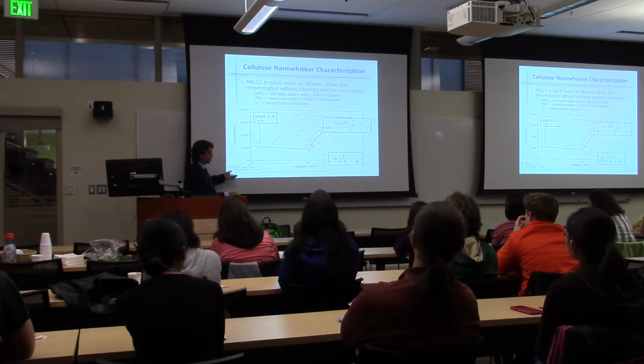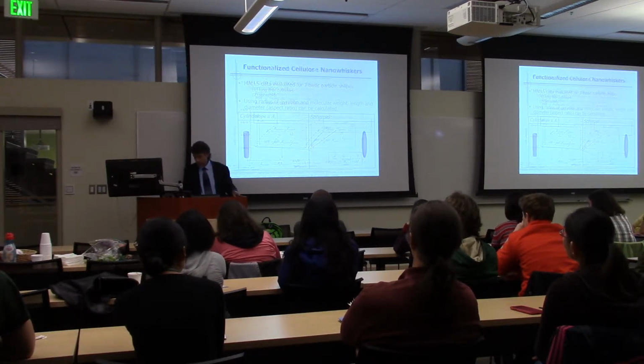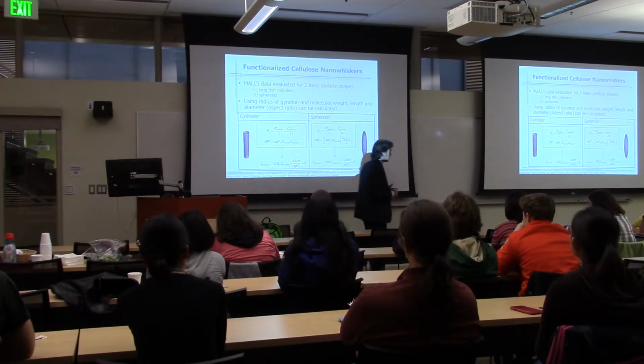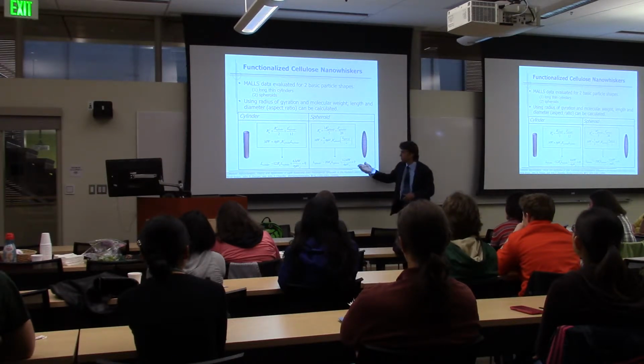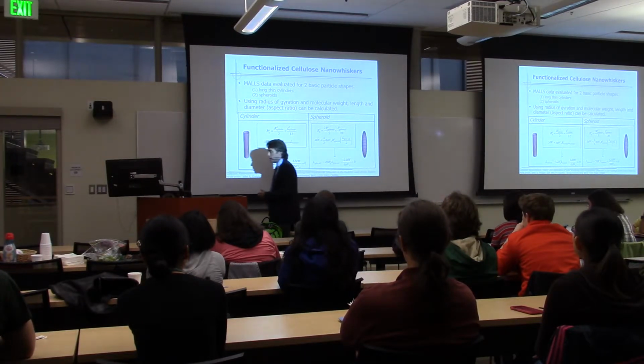Of course, the other thing that it gives us directly is the radius of gyration. So in here it says that the root mean squared radius of gyration is 220 plus or minus 8 nanometers. And so we can think about these nanowhiskers as being either cylinders or spheroidal ellipsoids. And it turns out, because it's crystalline cellulose, we know the density. And there's just a simple cubic equation, which comes from a mass balance here if you know the molecular weight. And so you can actually get at the length to diameter ratio, i.e. the surface area of the spheroid, by simply measuring the radius of gyration. And so now we do know the surface area to volume ratio for our materials.